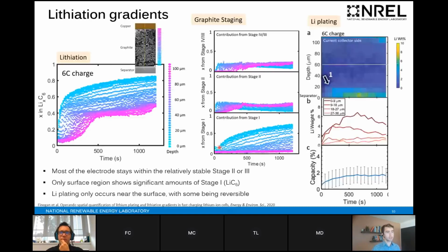And with X-ray diffraction, we are also able to detect plating. So on the y-axis is depth, on the x-axis is time. The color now is lithium weight percent, so it's pure lithium metal. And so we can see the growth of lithium metal close to the separator, which correlates roughly with the depths of high concentration of stage 1, down to about 20 micrometers.